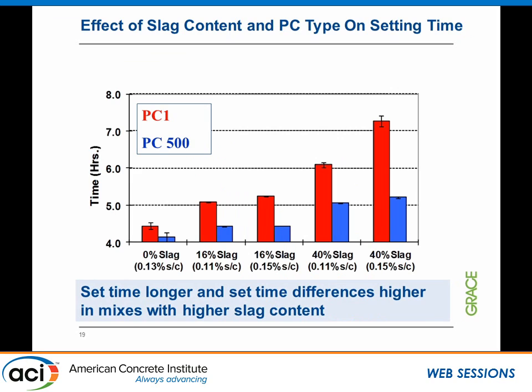And in here, we show you an example of a slag. Whereas in here, we have a 16% slag level versus a 40% slag level. We picked 2 of the chemicals that we had in the previous slide, and you can see that the difference between the 2 polymers at a different slag level is highest when we have more slag in there.